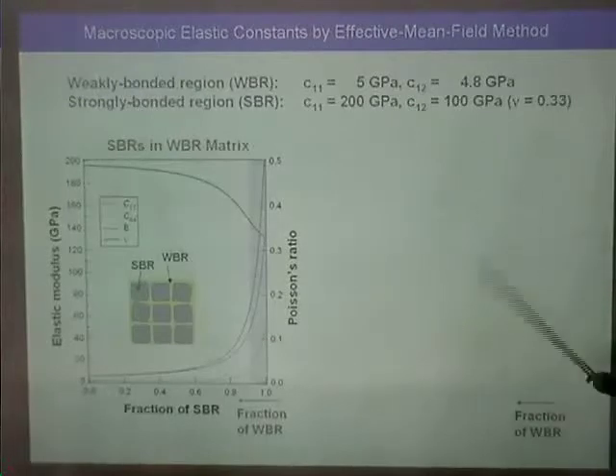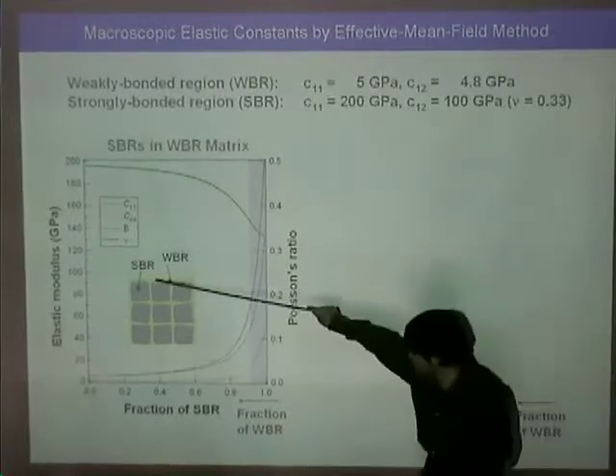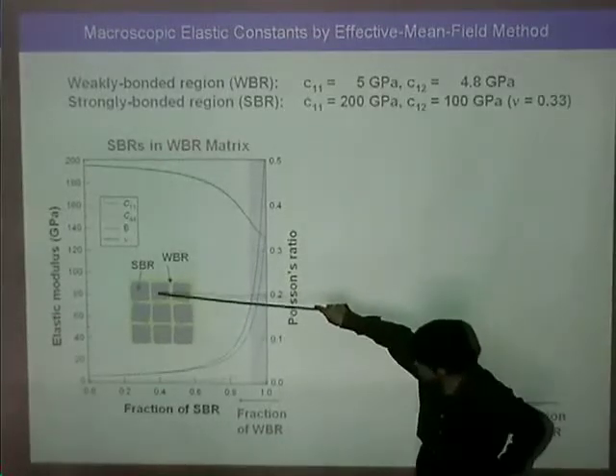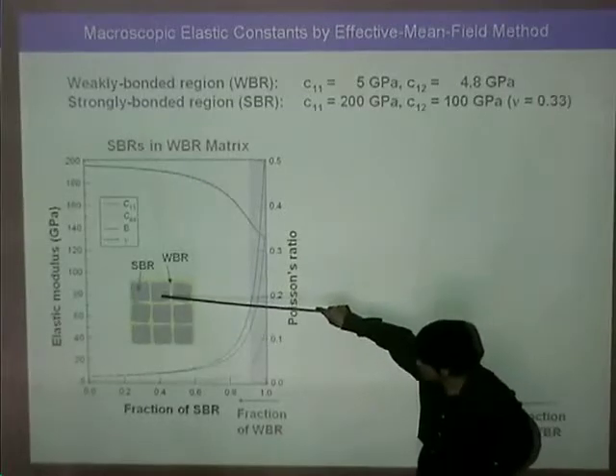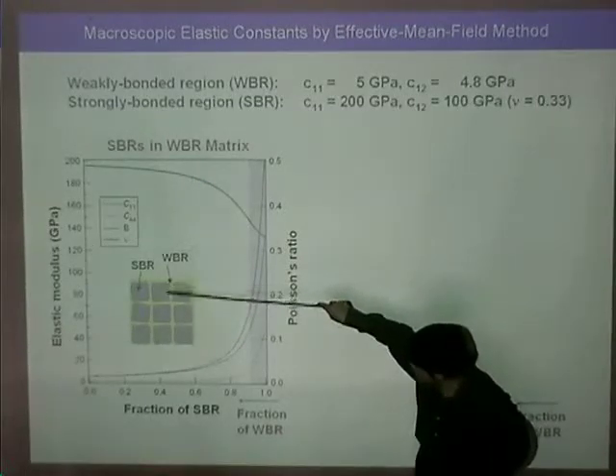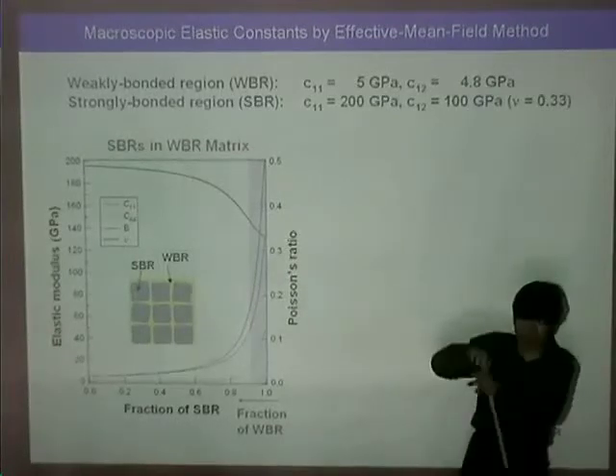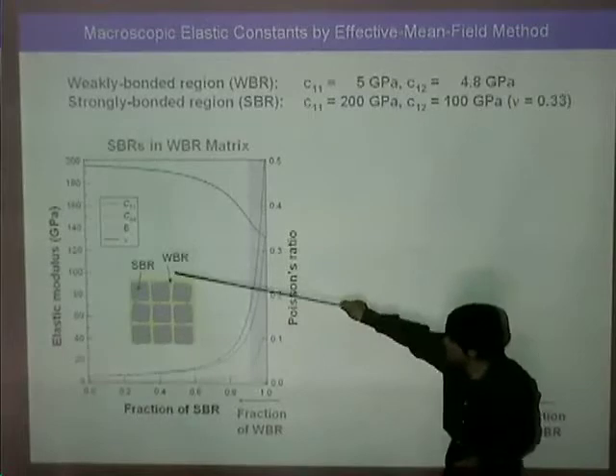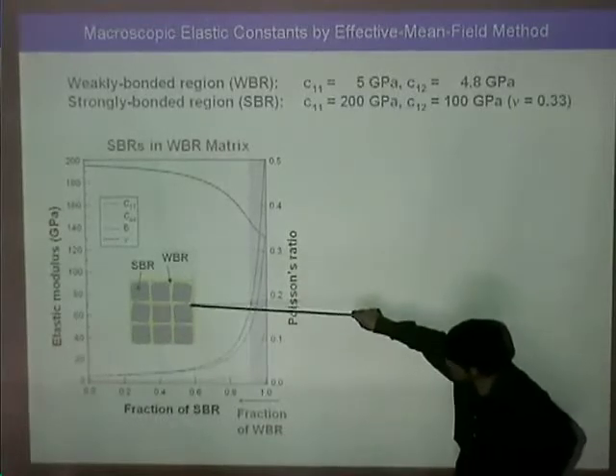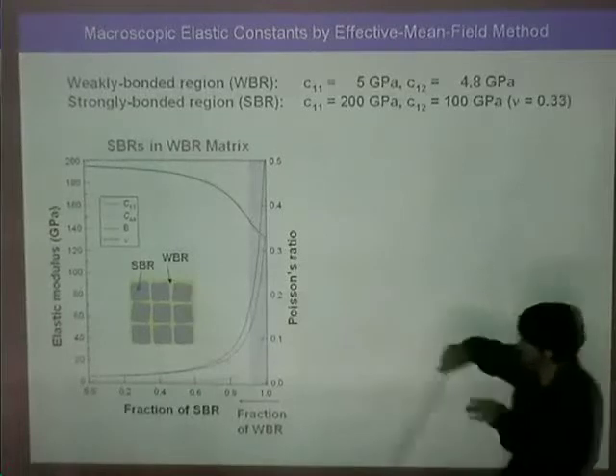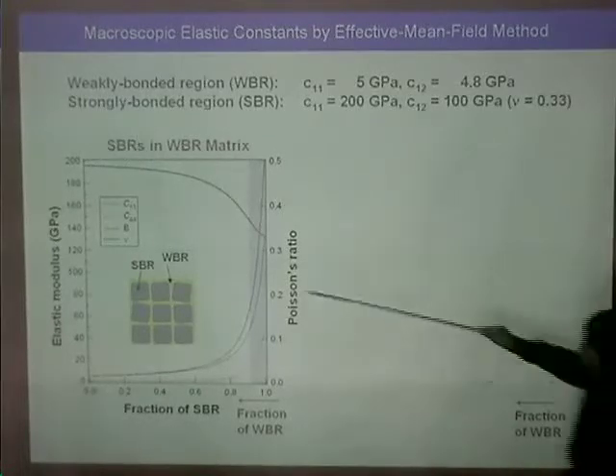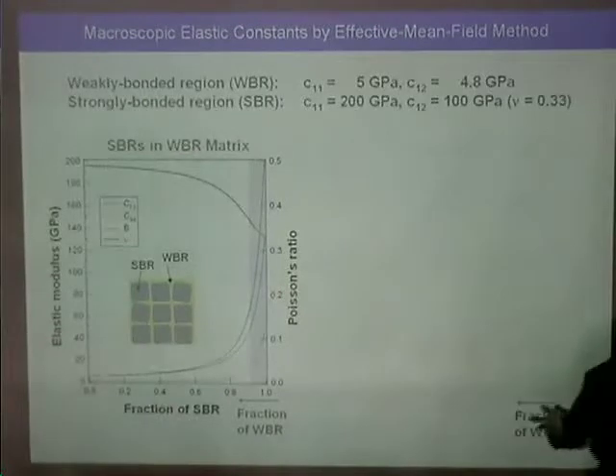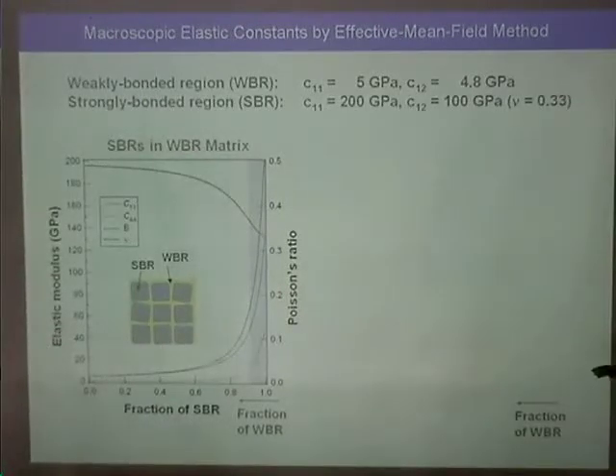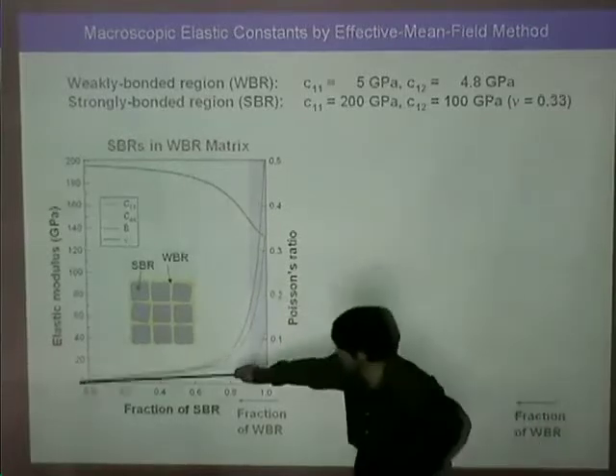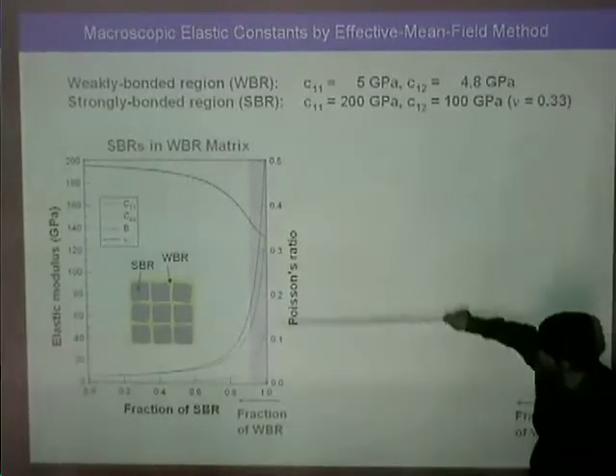So in order to explain this large change, we have proposed this softer model. This model has SBR, strongly bonded regions, surrounded by the weakly bonded region. When the SBR is surrounded by the WBR, the macroscopic elastic modulus becomes very, very soft. So for example, this is the WBR elastic constant, and these values.